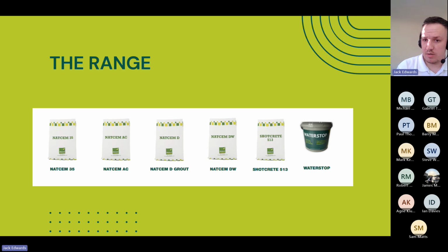We've got NATCEM AC, which can be used for minimum 3 millimeters, can be used as an anti-carbonation coating, for a sort of fine concrete repair material. It uses a fine grout. We've got NATCEM D, which is grout. That is a really fine, free-flowing grout that can be used down to virtually less than a millimeter. Very, very fine, very free flowing. Got very low compressive strength. It's got potable water approval, so ideal for use in any application around potable water, generally in terms of just general void filling, stabilization, wherever it may be.